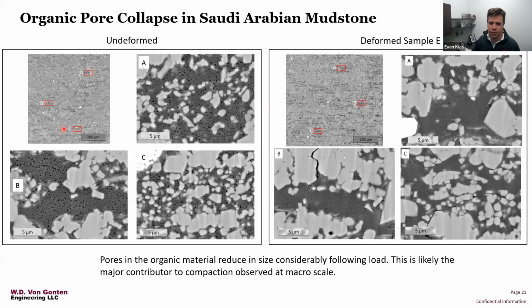We have a large mosaic with 3 locations within it, denoted by these red boxes. Prior to testing, you'll notice a pretty consistent pore size distribution throughout the image. You can see in each of these images nice large pores.